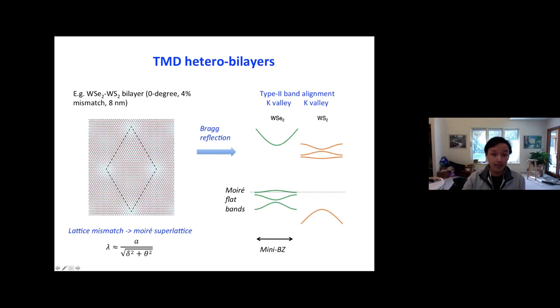And now, if you imagine that you actually reduce the twist angle of this bilayer to nearly zero degree, because the two materials actually have a 4% lattice mismatch, as a result, it forms a moiré superlattice structure even at perfectly 0 degree alignment. Due to that lattice mismatch, the moiré period is given by this formula. A here is the lattice constant of the WSe2 layer, and delta here is the 4% lattice mismatch. So basically, due to this lattice mismatch for small twist angle, the moiré period is actually not that sensitive to a small change in twist angle. Okay, so the structure will pretty much look like this as long as you don't really change the angle, measured in radian, by about 4%.